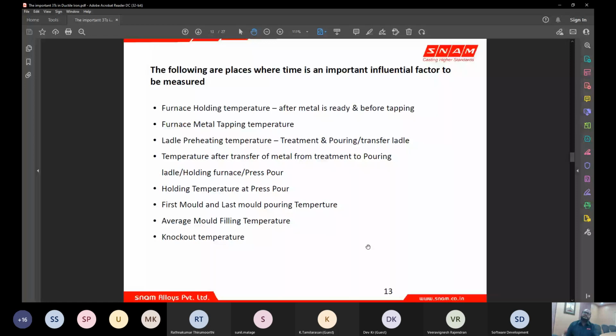The next is the temperature after transfer of metal from treatment to pouring. Here it is about the loss in temperature. This is the time where we add our inoculant, during transfer from tapping to a pouring ladle, or from tapping to a press pour or an automatic pouring system. So the temperature at which the inoculant is added and the transfer is happening has an impact on the nuclei which are about to come into the liquid metal, and on their stability. So we need to maintain the minimum required temperature such that you don't get any filling defects or pouring defects. That is the temperature sufficient for casting. Anything above that is going to kill all the special additives which you have already added to the liquid metal to obtain good ductile iron castings.